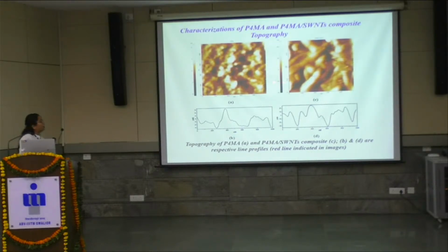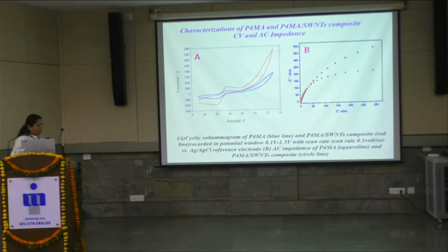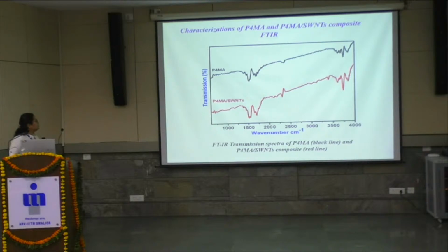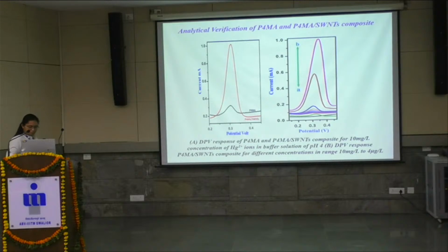When we talk about an electrochemically active surface, the roughness plays a great amount of work. So again, the characterizations were done utilizing CV, cyclic voltammetry, where we can confirm the more electroactive nature of the nanocomposite. Again, the AC impedance spectra, where again the good electroactive nature of the composite is addressed. Now this is FTIR for confirmation of the nanocomposite. Now this is a graph of the analytical study.